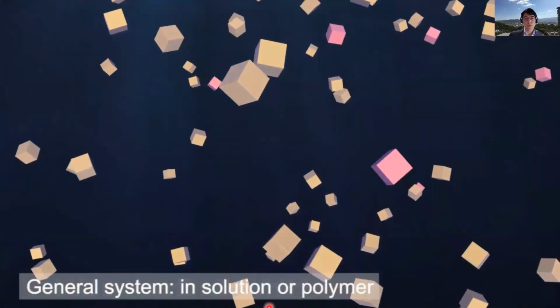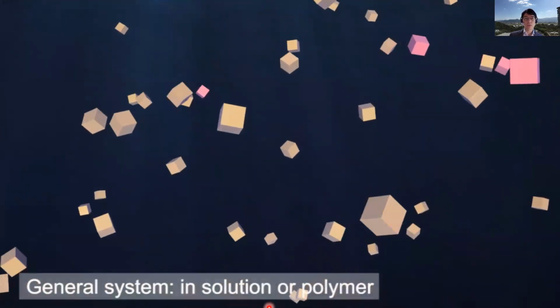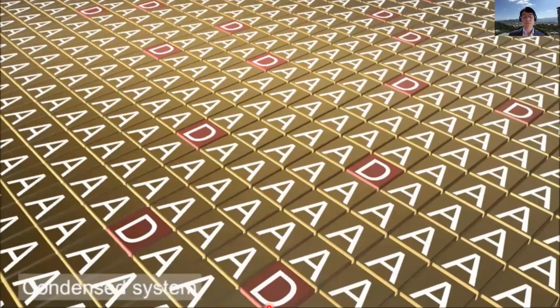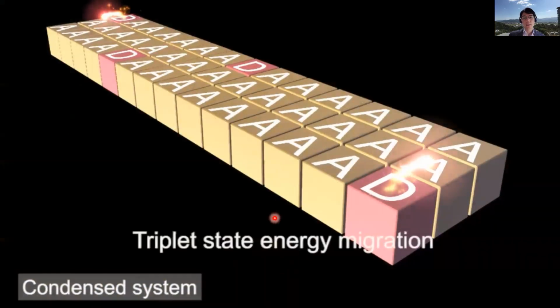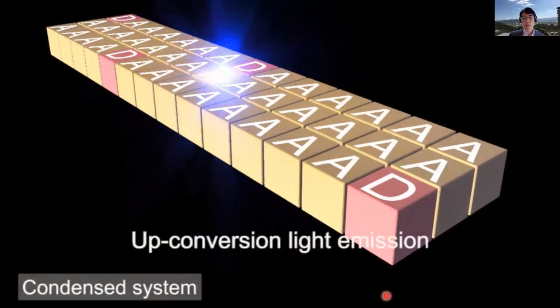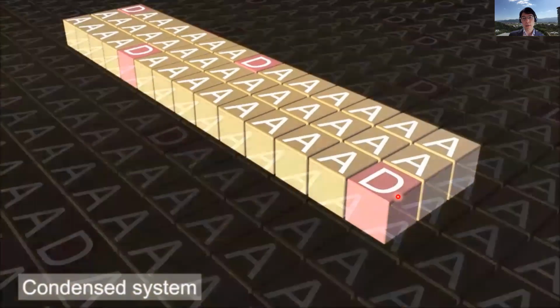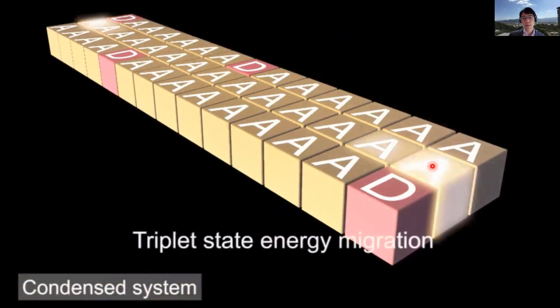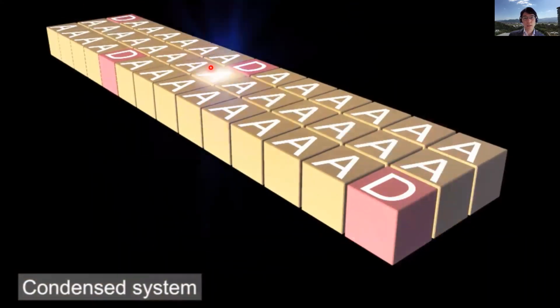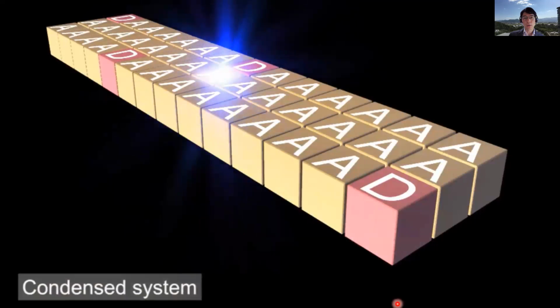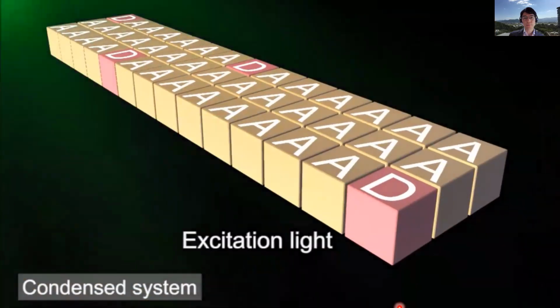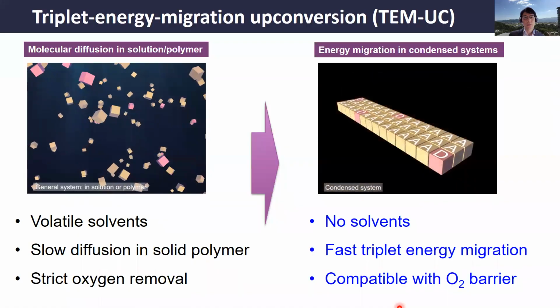But we have been proposing to shift from this molecular diffusion to energy migration. In this dense assembly of acceptors doped with donors, the donor transfers the energy to the neighboring acceptor, and this sensitized acceptor exciton can diffuse to show the upconversion. But why do we need to do that?